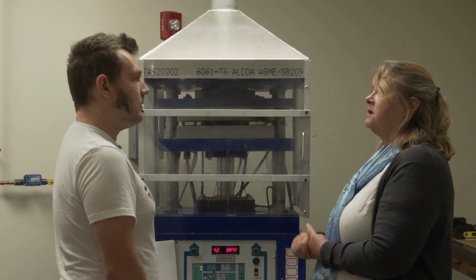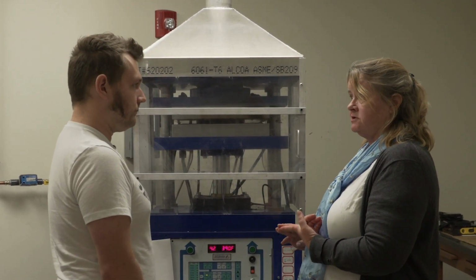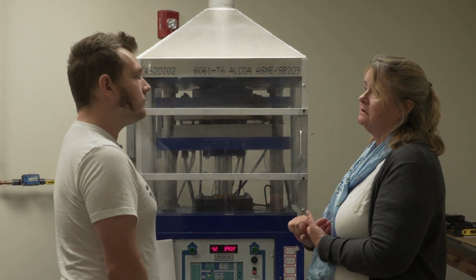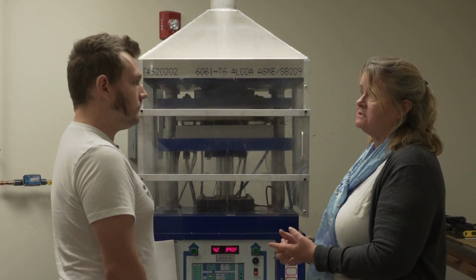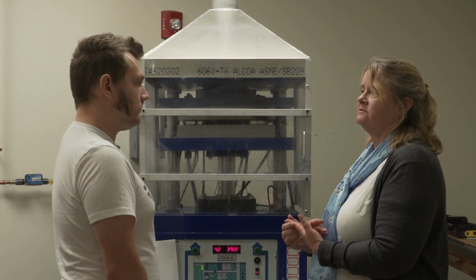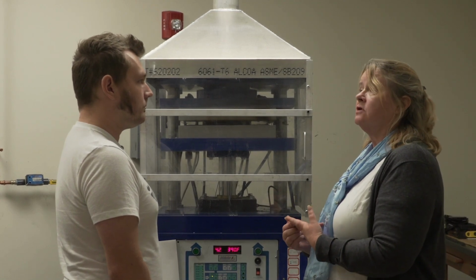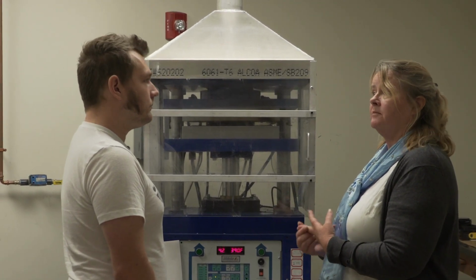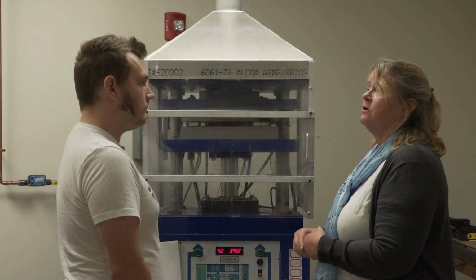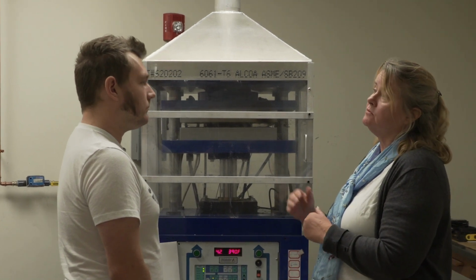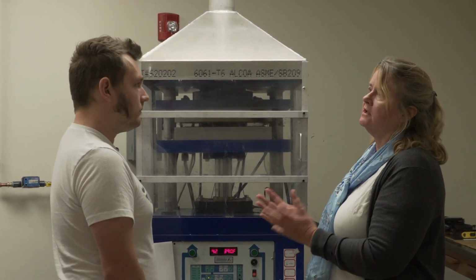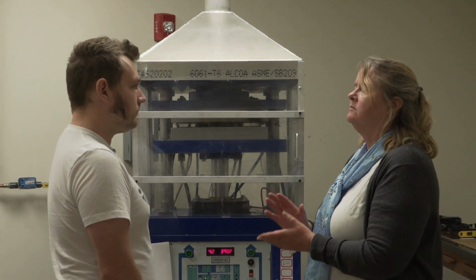So while we're heating this up, we bring the temperature of the wet gel up above 500 degrees F, 260 C, and the pressure is also rising during this time, probably up about 2,000 psi. So we're above the supercritical point of methanol. Now we've got methanol and water in there, but just a little bit of water, mostly methanol.